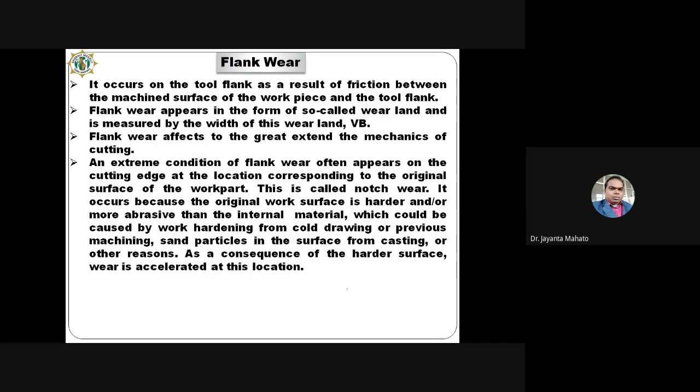An extreme condition of flank wear often appears on the cutting edge at the location corresponding to the original surface of the workpiece. This is called notch wear. It occurs because the original work surface is harder or more abrasive than the internal material, which could be caused by work hardening from cold drawing or previous machining, or by sand particles in the surfaces from casting or other reasons.